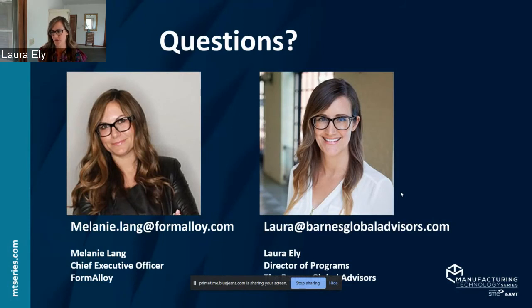So sometimes with these larger melt puddle DED processes, like some of these wire-fed ones, you have to take a look back at how you analyze that, because some of the fatigue performance that has been analyzed on these can actually be really good, because you don't necessarily have any little stress concentration sites within it. So unfortunately, there's no easy answer. The answer is it depends. But just like what Melanie said, each of the DED processes has a sweet spot, and you can always optimize for surface roughness. And more importantly, it's not even just about the surface roughness, but whatever end performance requirement you're trying to meet.